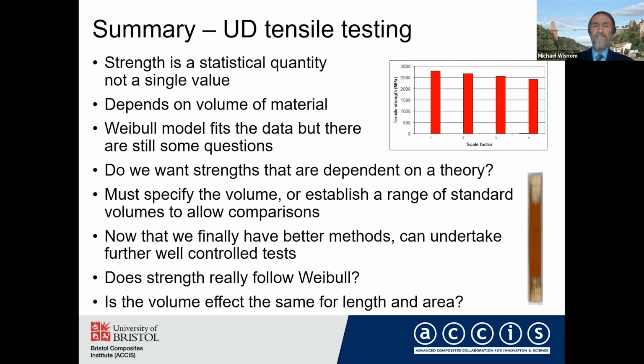So I think the key to this is that when we do carry out tests, we must specify the volume. Or maybe we should be having a range of standard volumes which will allow comparisons between different materials, but without necessarily having to get into the details of the theory that backs it up. Now that we do have better methods available, then I think we should undertake further well-controlled tests to really look at these things in more detail based on really sound experimental methods.